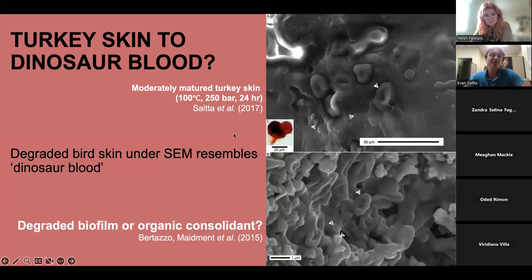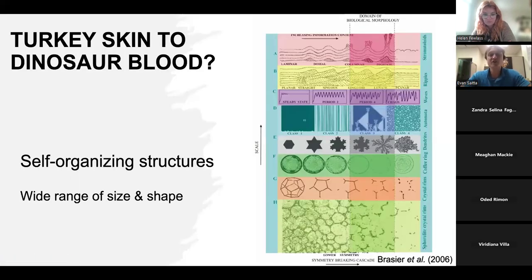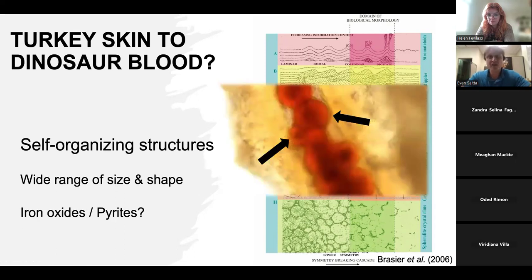And so this surprise result through maturation suggests that these are not red blood cells, but maybe degraded biofilms from microbial communities living within the bone, or potentially degraded consolidants from glues that might have been applied to the fossils. And so in this case, those structures are not biologically formed blood cells. They are self-organizing structures that have a wider range of sizes and shapes than what would otherwise be produced through controlled biological processes. And then other claims of dinosaur blood cells might also match this, but rather than organic folds, they might be things like iron oxide or pyrite framboids. So for example, here's two putative dinosaur blood cells next to each other, and you can see that there is a wide range of size, even in completely adjacent structures.